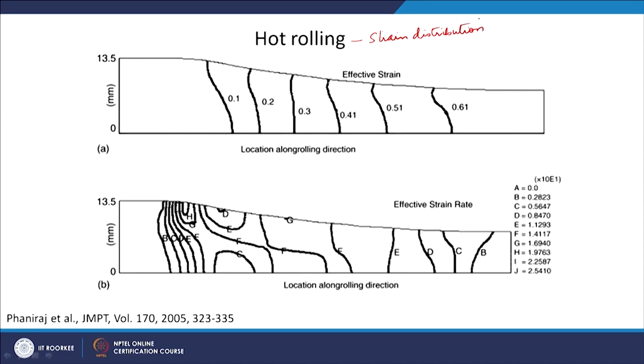You can see that on the x-axis you have the rolling direction, and the y-axis is the thickness of the material. This is some work I have taken from the Journal of Material Processing Technology. What they are trying to show here is the strain distribution at different stages during the rolling. The roll must have started somewhere from here, and somewhere here the roll must be coming out. You can see how much strain is introduced at different stages, from 0.1 strain going up to 0.61 strain. In the second slide they are also showing the strain rate distribution, and the values are given here.